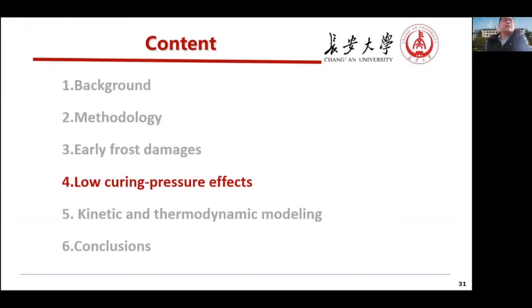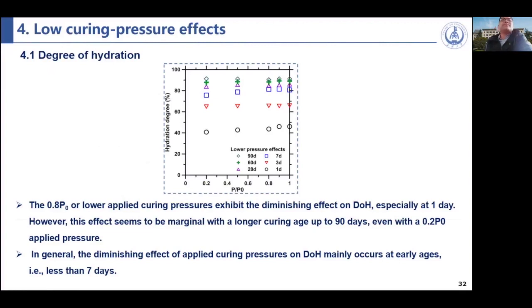We will introduce some conclusions and what we learned before about the lower curing pressure effect, especially on the microstructure. This is the degree of hydration during the lower pressure. We carried out the study under 0.2, 0.5, 0.8, and 0.9, and the P0. So we can see that during the first day of the hydration, the lower curing pressure affects the hydration degree, but at the later stage, up to 3 days later, the curing pressure has less effect on the degree of hydration.